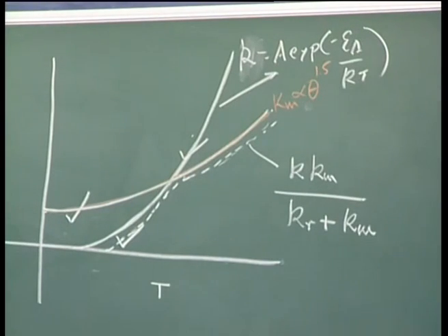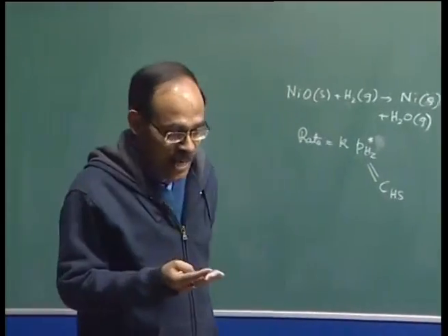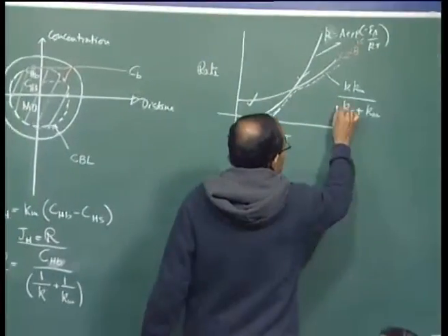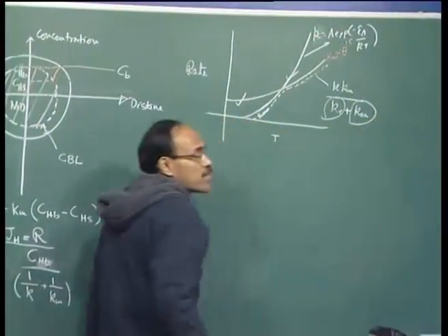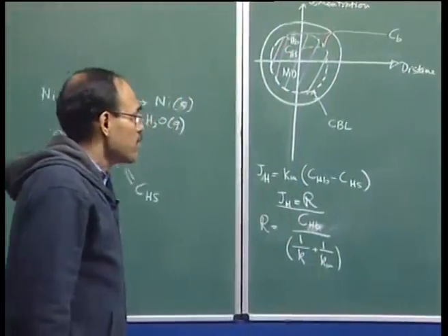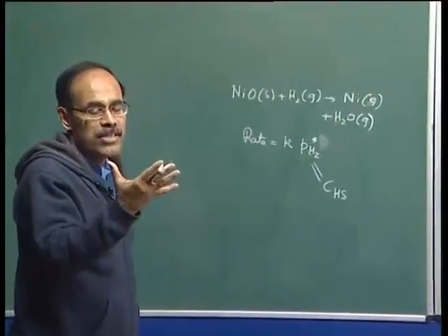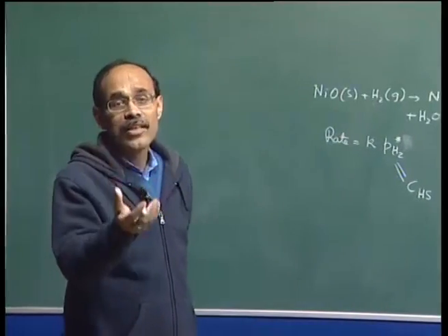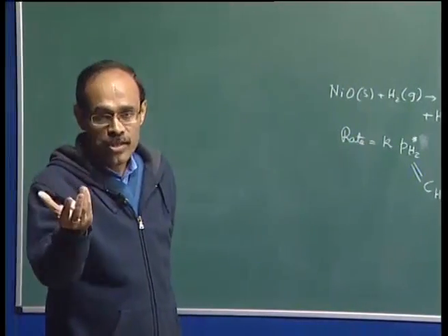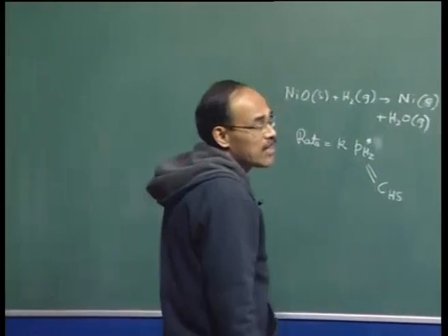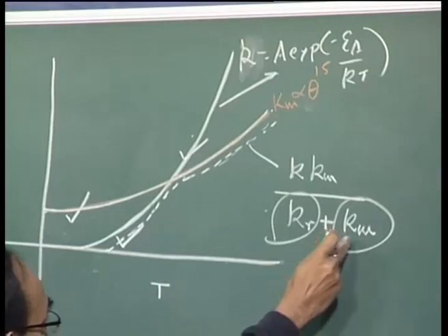So, therefore, it is mass transport control, and the equation boils down to this. Now, on the basis of this, you can find out the value of this, and then you can conclude which is the rate limiting step. Whichever step shows the largest resistance controls the rate, and these are a direct measure of the resistances to mass flow.